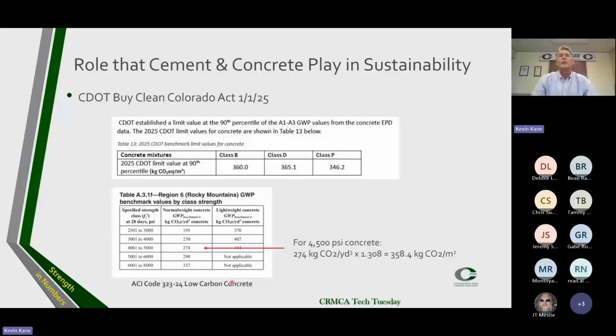So if we convert cubic yards to cubic meters, we take the 274 kilograms of CO2 per cubic yard, multiply it by 1.308, and we come up with 358.4 kilograms of CO2 per cubic meter. Oops, not square meter, cubic meter. And that's pretty close to what CDOT came up with. So these are very attainable values, and we've been doing these for a while. In fact, if you look in ACI 323, the Rocky Mountain region is already the lowest or lower on global warming potential than the other regions around the country. So we're already a little bit ahead because Colorado is a pretty green state.